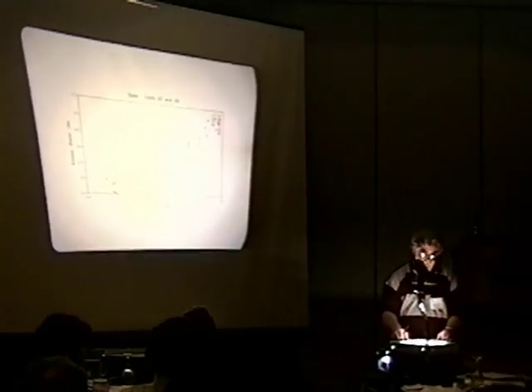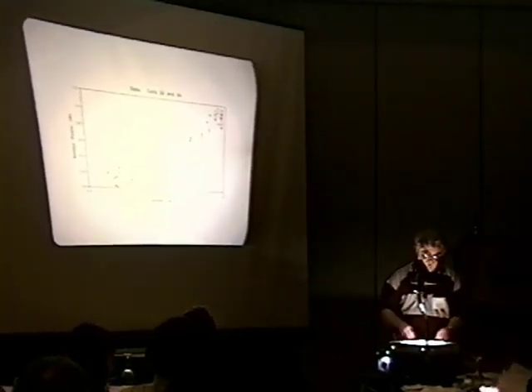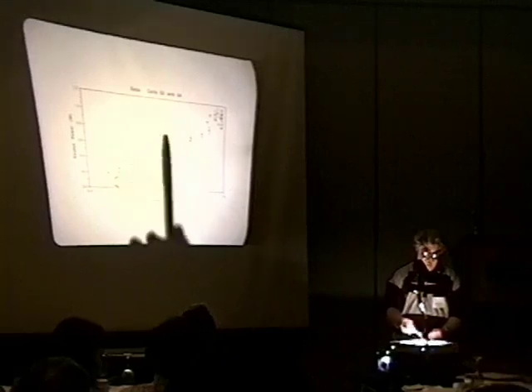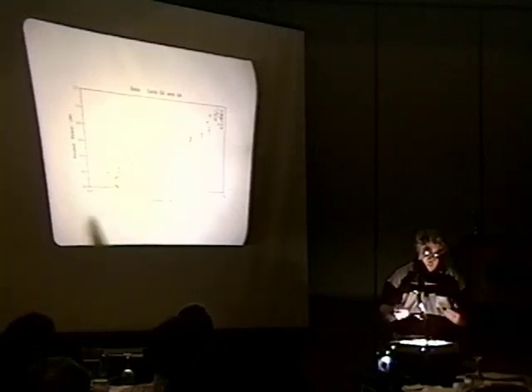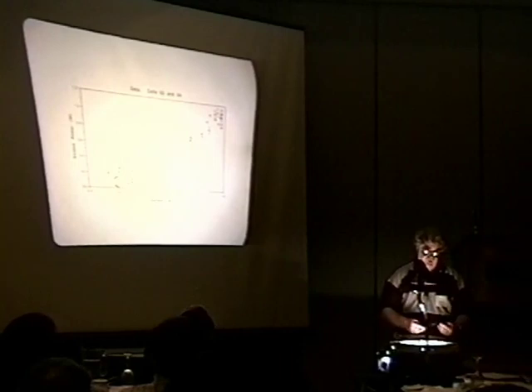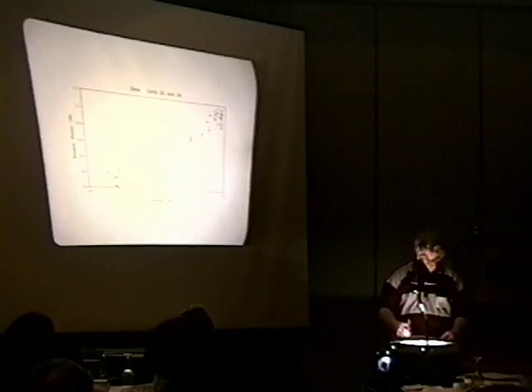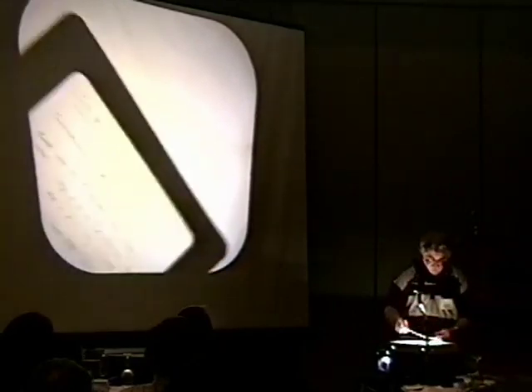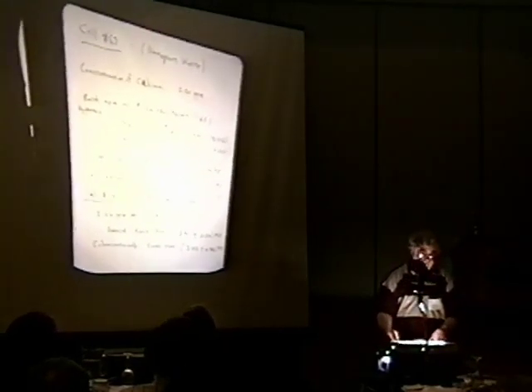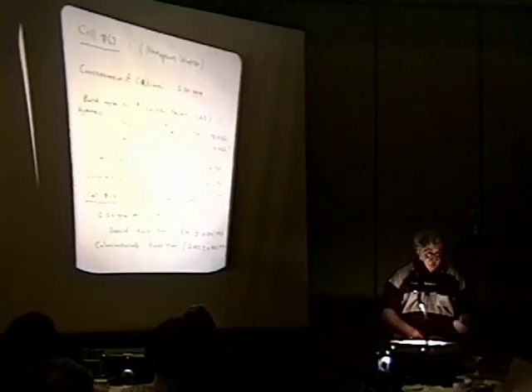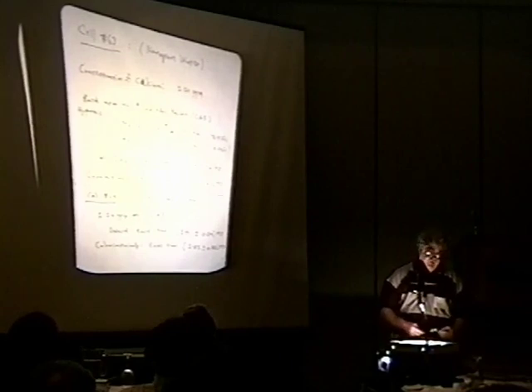The deuterium-depleted water from Aldrich, and here is cell 64. The previous data has the error bars left off, and the cell 64 deuterium-depleted water cell has the error bars put on, but you can see the performance is very, very similar there. Very little difference. Okay, and if we look at the analysis of the electrolyte, we find again evidence that the reaction potassium to calcium by picking up a proton is the driving reaction here.